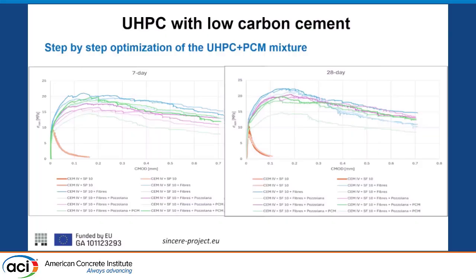The flexural performance, by the way, with fibers is not only the peak strength, but we performed the test with a notch in crack mouth opening control. So you can see this is the toughness that we obtained for all the mixes that we tested. And if you compare with the plain matrix, you can see the great amount of energy dissipation capacity and toughness that we were able to obtain.